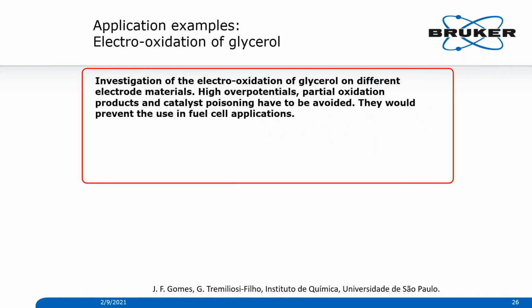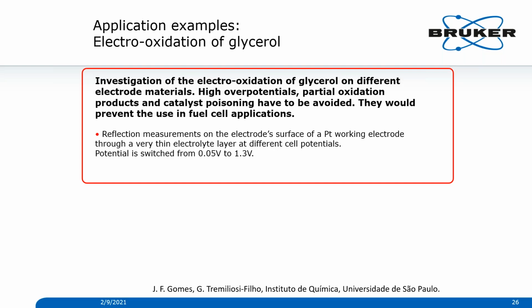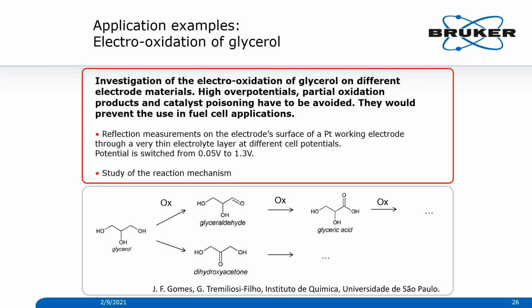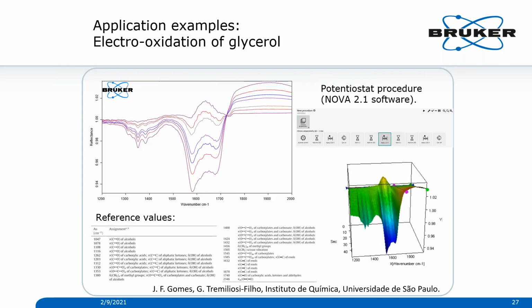Another application example is the electrooxidation of glycerol. What we did here was reflection measurements on the electrode surface of a platinum working electrode through a very thin electrolyte layer, at different cell potentials, switching the potential from 0.05 volts to 1.3 volts, to see what kind of reaction mechanism was going on during this reaction.